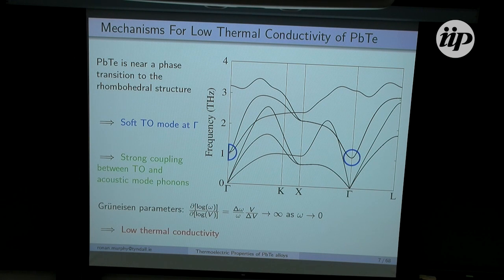And you can see an indicator of this if you look at the Grüneisen parameters, where as the frequency gets smaller, the Grüneisen parameters get larger. So ultimately, what we see is that this large TO-acoustic interaction in lead telluride results in very low phonon lifetimes, which give rise to its characteristically low lattice thermal conductivity.